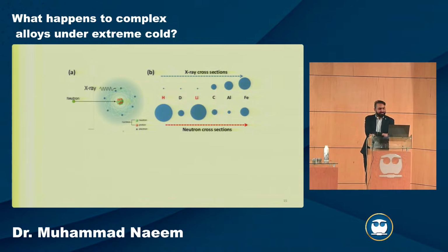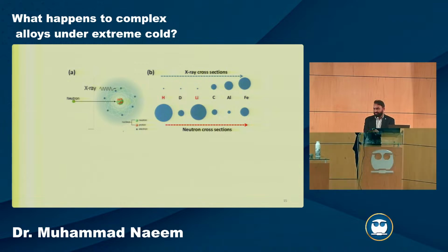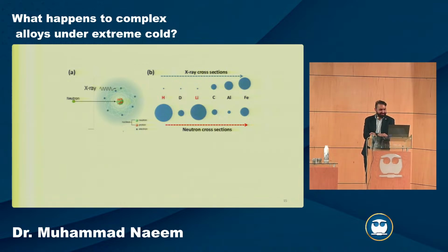When they interact, you see the cross section of X-rays increases with atomic number, right? So it is easier to probe heavy elements, or high atomic number elements. Then it has its own limitations; at a certain extent you cannot do much about it. But with neutrons, you can see hydrogen has a very large cross section. Then deuterium, which is an isotope of hydrogen, is different from hydrogen itself, and it's not atomic number dependent. So for certain elements it can be very helpful, but for others, for example boron, you cannot choose it unless you want to not get anything out of it.